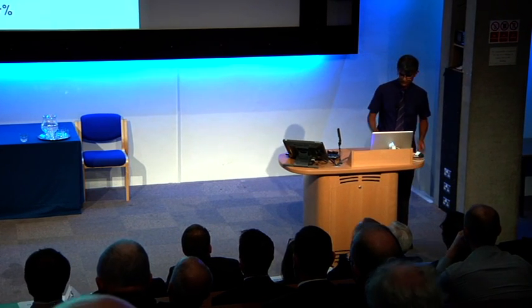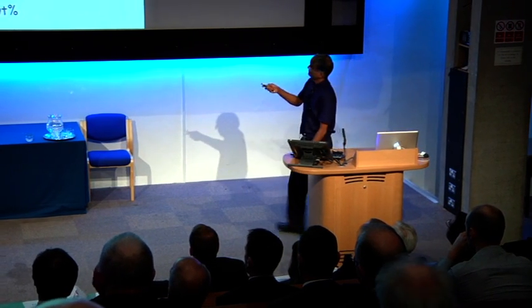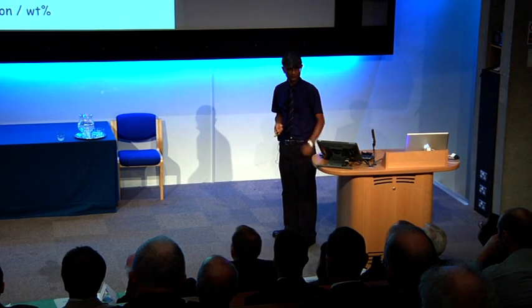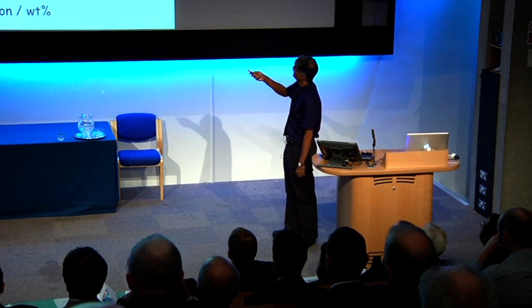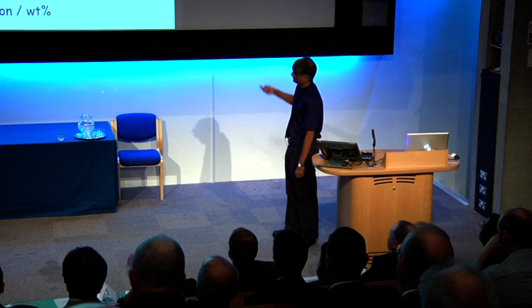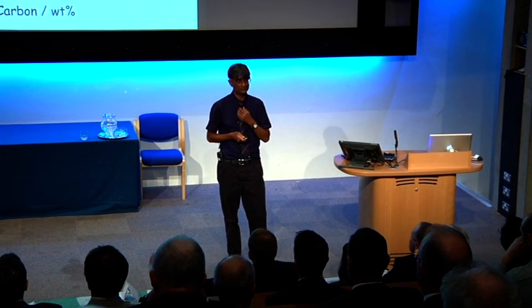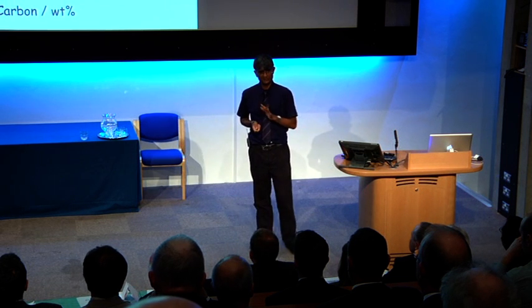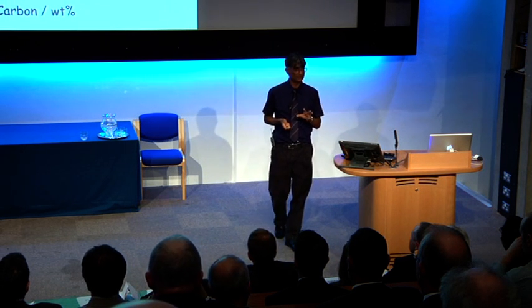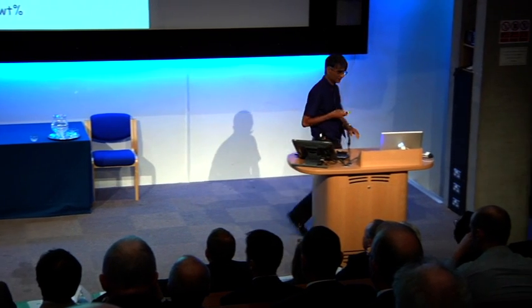Well, as I said to you, we have the theory, we do the calculations, and according to this, so this is in Kelvin, so this is room temperature here, we could produce bainite at room temperature. This is the martensite start temperature, this is the bainite start temperature. If I put sufficient carbon in my material, I could get bainite at room temperature. But this isn't enough, we've got to also have some kinetics into this. And if I do produce bainite at room temperature, it would take me about 100 years.